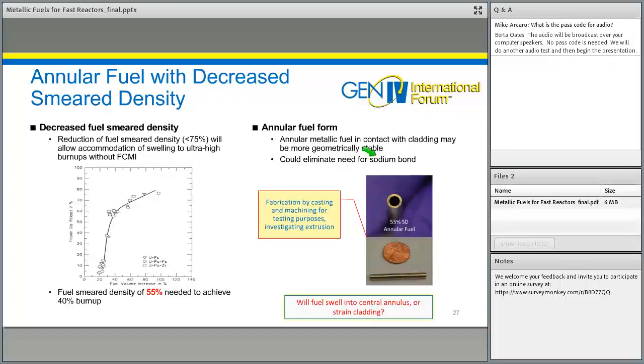And an additional feature of an approach like this is if you don't have a large fuel cladding gap, you essentially have no fuel cladding gap. You put all your void space into this annulus. Now you don't have a need for sodium bond. And in fact, most of our annular fuels that we're testing have no sodium bond in them.